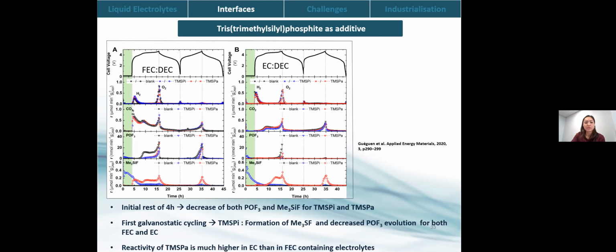So this is an NMC full cell with graphite. They have FEC-DEC and EC-DEC, and we can see that the two main gases produced are POF3 and Me3SiF. We can see that there is a suppression of these gases when the additives are used. The electrolytes do not produce these two gases, which can be detrimental to the cell performance.